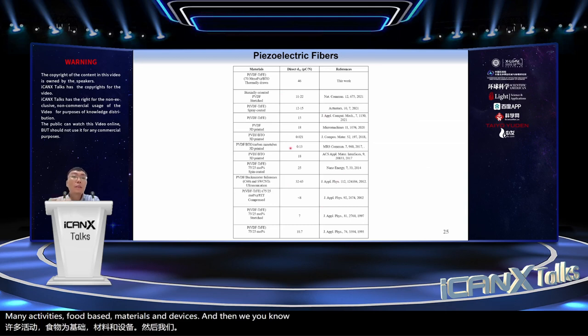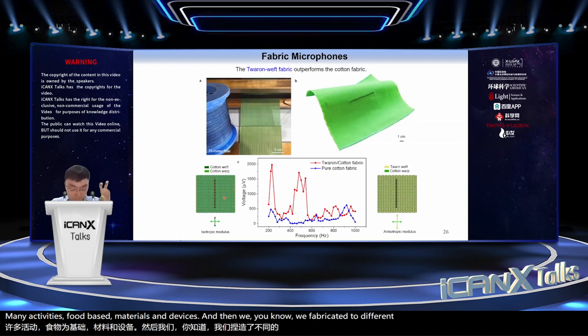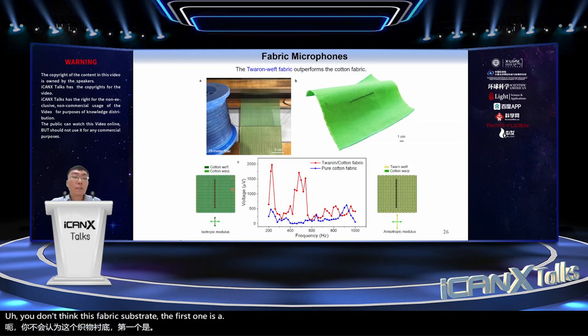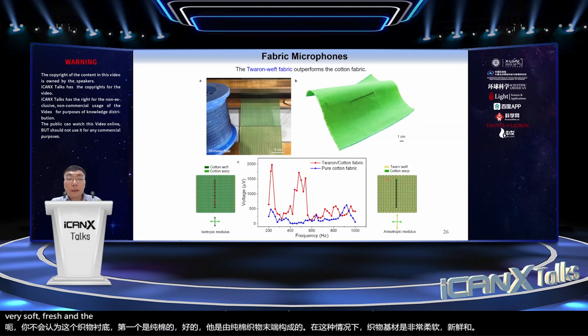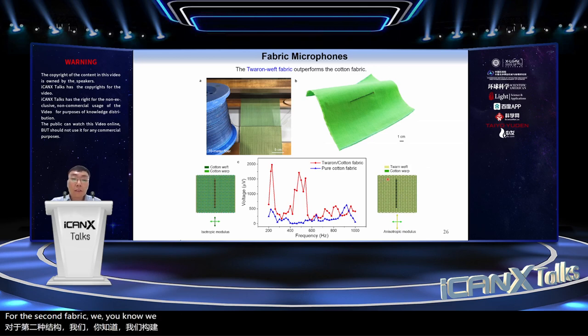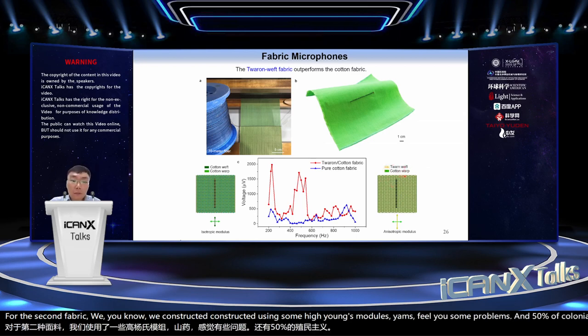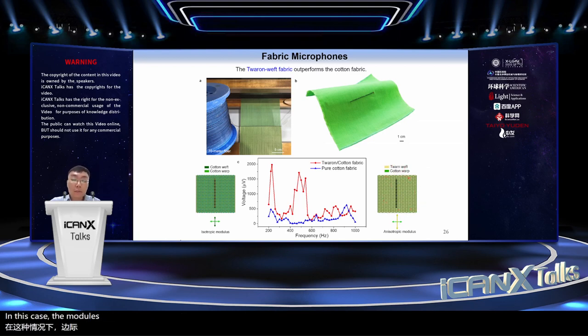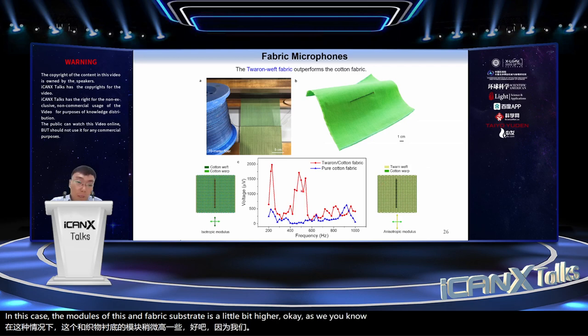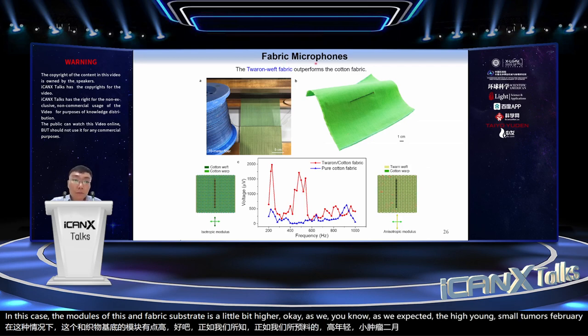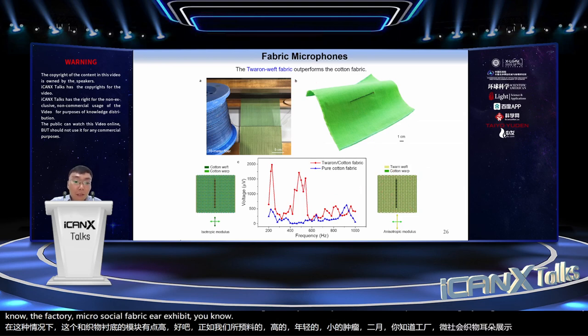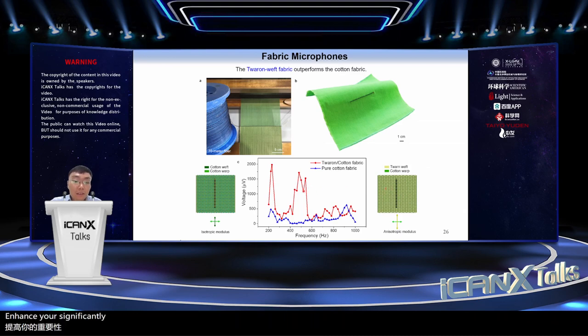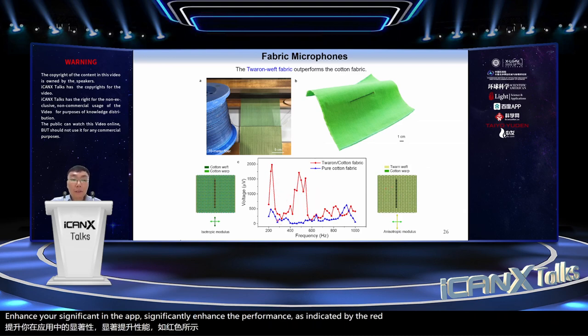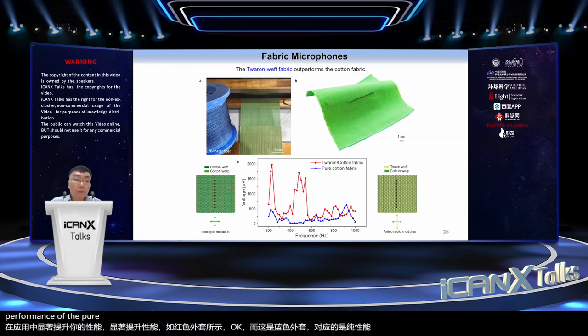And then we fabricated two different fabric substrates. The first one is constructed of pure cotton fabric, and in this case the fabric substrate is very soft. For the second fabric, we constructed it using some high Young's modulus yarns. Here we use 50% Twaron yarns and 50% cotton yarn. In this case, the modulus of this fabric substrate is a little bit higher. As we expected, the high Young's modulus fabric, the fabric microphone or fabric ear, exhibits significantly enhanced performance, as indicated by the red curve. And this blue curve corresponds to the performance of the very soft pure cotton fabric.